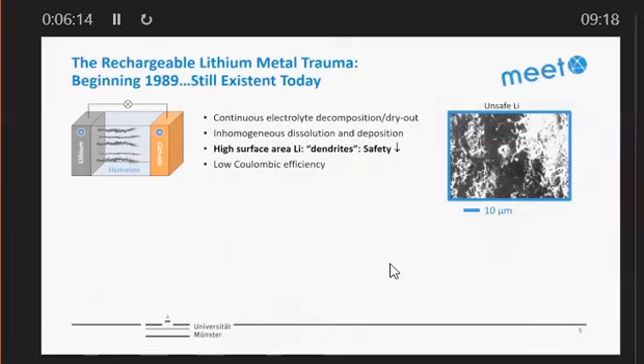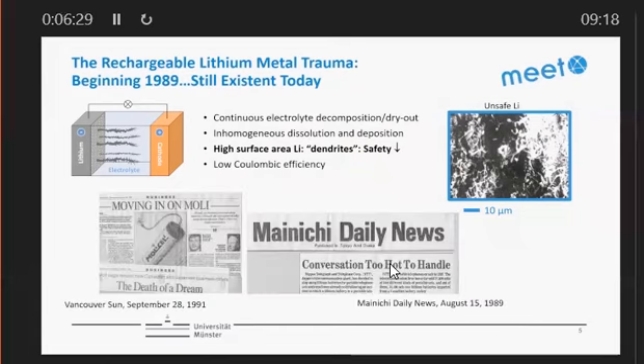And here you see a picture from my diploma thesis in 1992. So you see already at that time, we were able to make crappy lithium metal batteries with a lot of dendrites after charge. And this actually also came in the news, and you see the battery here looks like a dynamite rod. And also it really happened while telephoning, you know, this very big telephones at that time, bricks, called for obvious reasons with an antenna on top. They caught fire while calling, so conversation too hot to handle. And a lot of people who were working at that time gave up lithium metal work. This was actually the birth of the lithium-ion battery.